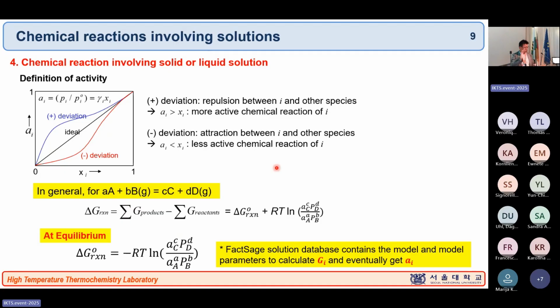So now, if you consider all these kinds of solid solution, liquid solution, and gas solution simultaneously, then we can properly understand the chemical reaction of the complex reaction. So for example, if you have A and B reacting together and making C and D, okay? The Gibbs energy of reaction, delta G of reaction, is equal to all the partial Gibbs energy of the products minus the partial Gibbs energy of the reactants. Then if you express this as a pure standard Gibbs energy and the activity, then you can collect it back in this equation here. And here, delta G naught of reaction is an important factor, but you have an additional correction term from the environment. How you set your environment, you can now switch this delta G naught, even if positive, to make it negative or make it equilibrium state. Okay? That's why we're doing engineering.